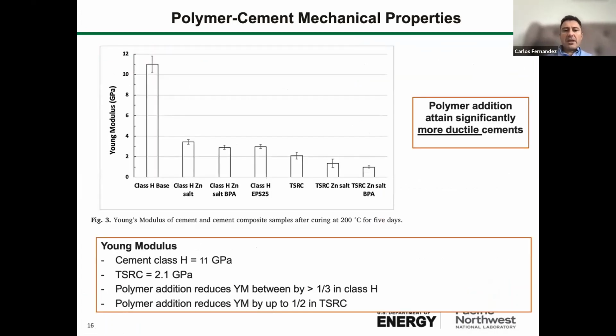Young's modulus, there were talks about that. Fibers reduce the Young's modulus. We want the material to be more ductile. Yes, with the addition of polymers, even adding 5% of the polymer produces a reduction in Young's modulus to about 1/3 of the Young's modulus of control cement. So the material is much more ductile, but still maintaining the compressive strength required after 24 hours.